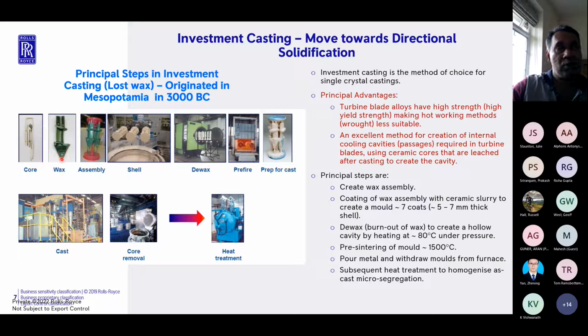So what you normally do is you have a wax pattern die, you place the core in the wax pattern die and you inject wax around the core. And effectively you get a wax pattern like you see there, but it's got an internal cooling passage given by the shape of this core. So effectively it's a composite between a wax and a core.